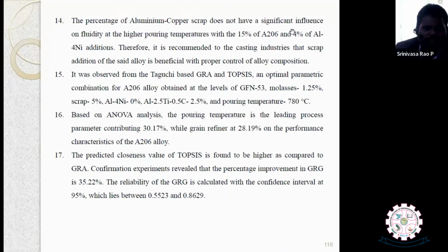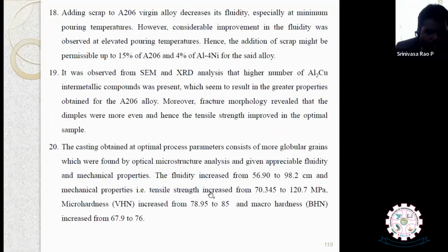Aluminum copper scrap does not have a significant influence on fluidity. Therefore, it is recommended to the castings industry that scrap addition of the said alloy is beneficial with proper control of alloy composition. These are the optimal compositions we have got by using GRA and TOPSIS. Based on the analysis, which parameter is contributing more is also decided. The predicted closeness value of TOPSIS is found to be higher compared to GRA. Comparatively, we see the predicted value is much closer in the case of TOPSIS.